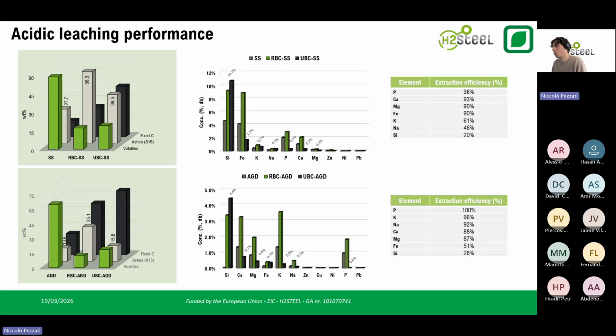Whereas for all those elements which we consider detrimental for steel making practices, we see here how it is possible to sensibly reduce all of them apart from the silicon. So the post-treatment is only ineffective on the silicon, which concentrates through the entire process, whereas all the other elements, so the iron, the alkali, the earth alkali metals, the heavy metals as well, and mainly the phosphorus are extracted in the acid leachate, so leaving the solid products free of any sort of these contaminants.